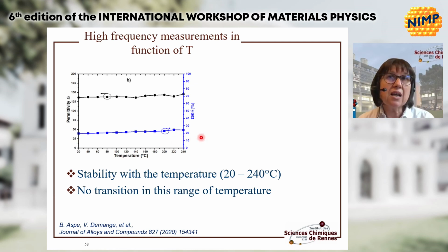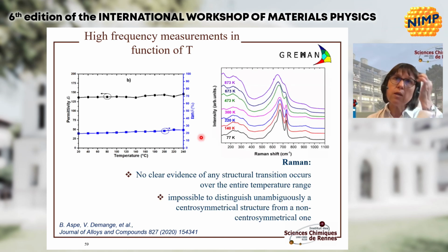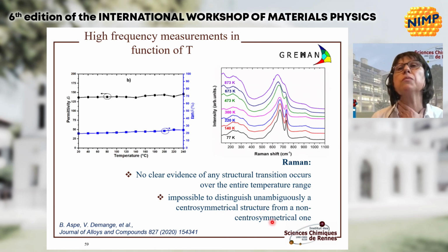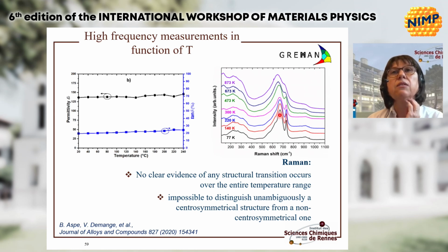What about the structure itself? By Raman spectroscopy, performed in a quite wide range of temperature, it has been impossible to distinguish unambiguously between a centrosymmetrical structure and a non-centrosymmetrical one, because we have quite broad peaks because of some local disorder in this composition and in this structure. And there is no clear evidence of any structural transition over the entire temperature range.